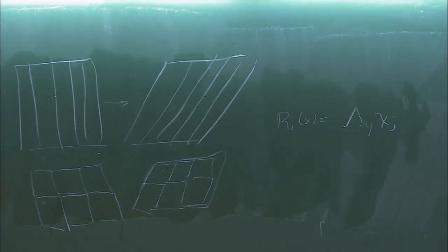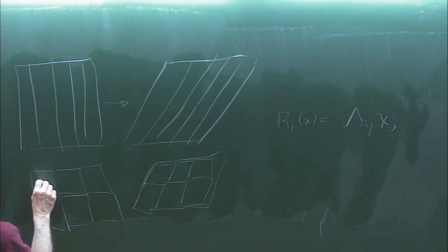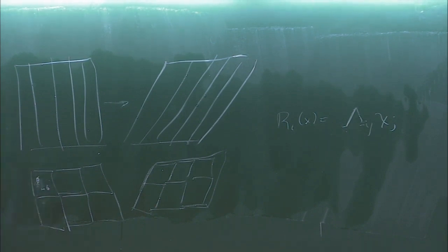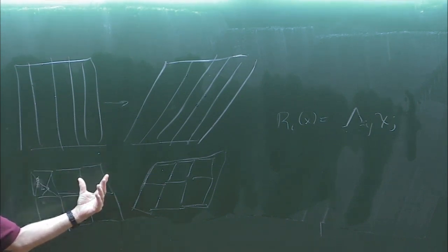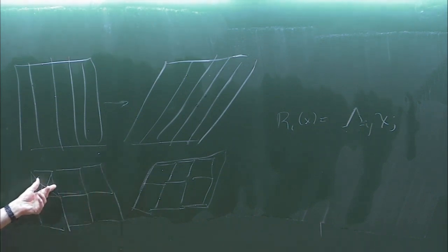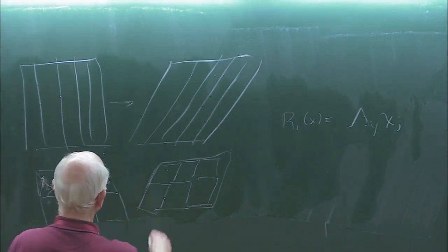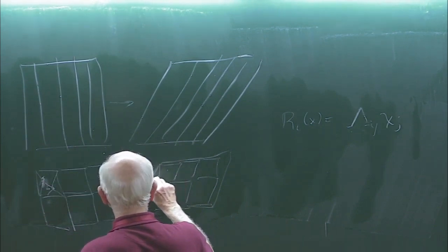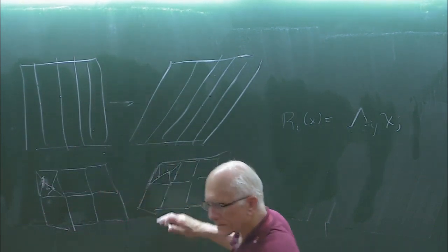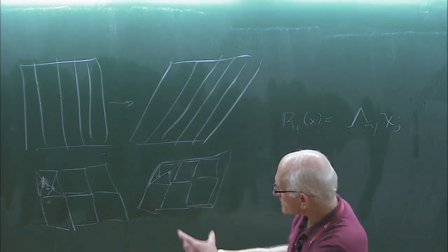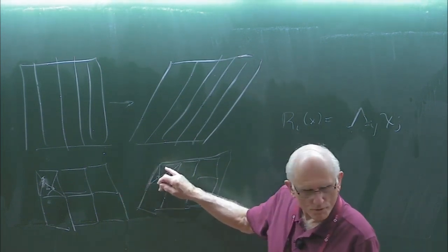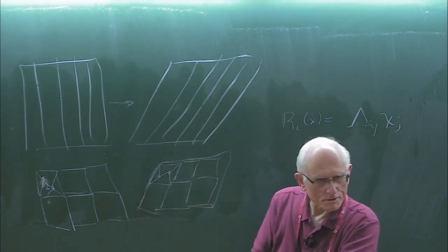Now, that's true for a cubic lattice and for some low index lattices, but suppose I put lots of atoms inside the unit cell. So let's just do something simple like this. And assume that there are bonds here that connect things like that. Now, what's going to happen when I shear this? Well, since it's periodically repeated, the unit cell itself has to have the same shape. But the atoms on the inside don't. And they will, in general, be displaced relative to what they were before. So this one might move down here a little bit, and this one might move up here. I'm not guaranteeing you that I've got the exact result for this form. But what happens is I've distorted the unit cell, and I've stretched some springs more than the others. And these are going to relax and go to a new position to lower the energy.